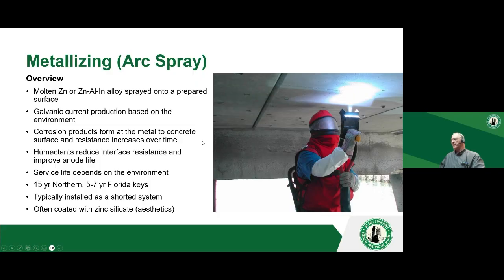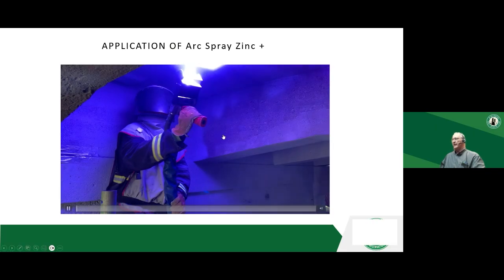and it's one of the more prevalent systems around water because it really requires a little bit of humidity. If you're in a moist area, for example, Toronto has used this quite a lot on their Gardiner Expressway and underpasses. If you use it on parking garages, typically you're going to use this on the ends of double T's on the stems because you don't have a whole lot of cover, and you typically have problems at the ends of the double T's because of leaking joints.